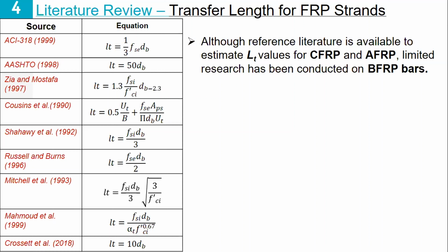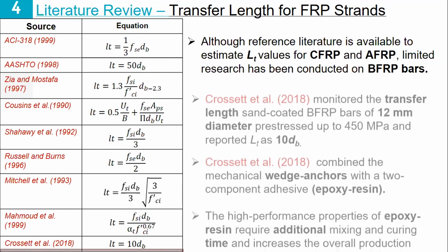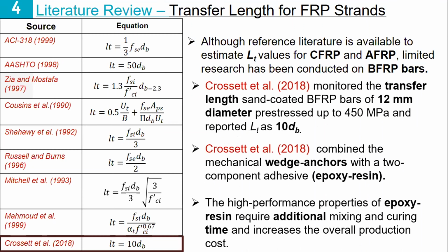However, for BFRP, very limited research has been conducted, and one of these studies was conducted at Queen's University Belfast by Philip Crossett, a PhD student of Professor Sue Taylor. In order to determine the transfer length, Philip had to deal with the fact that there are no readily available mechanical wedge anchors for these types of bars, because these bars have very low transverse strength.